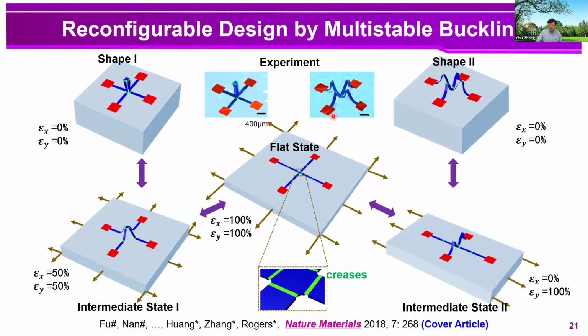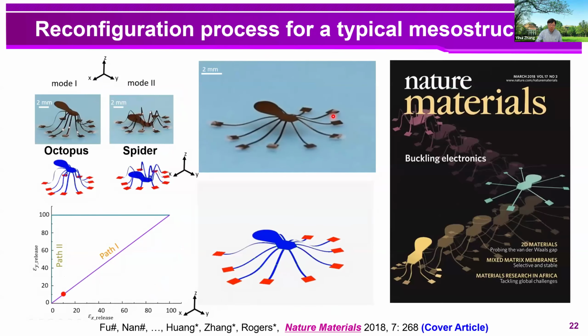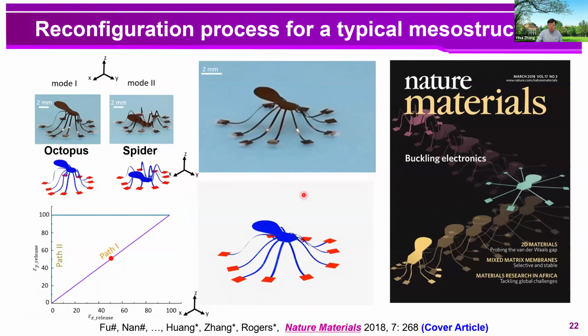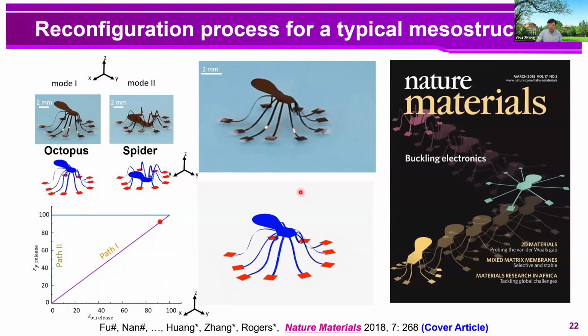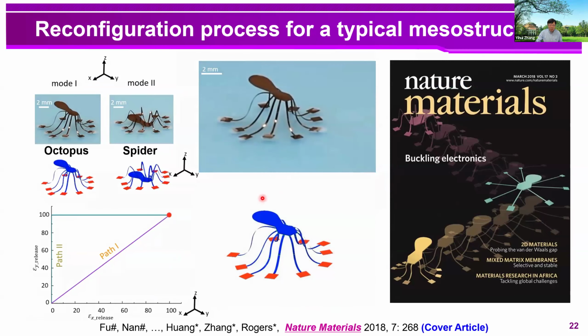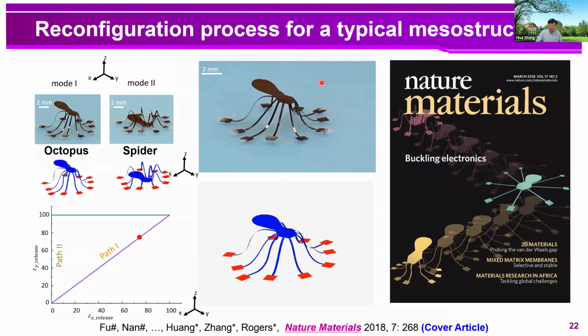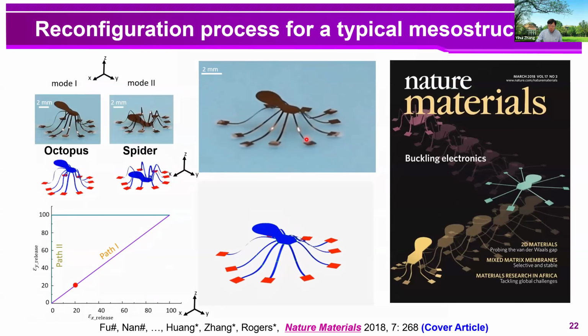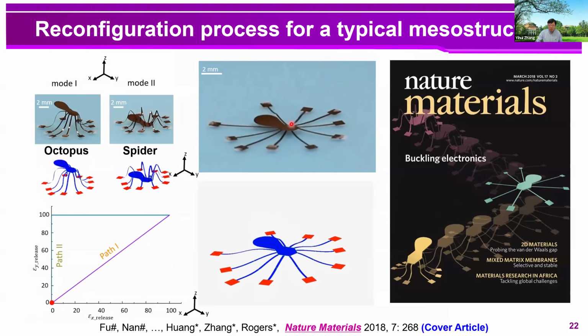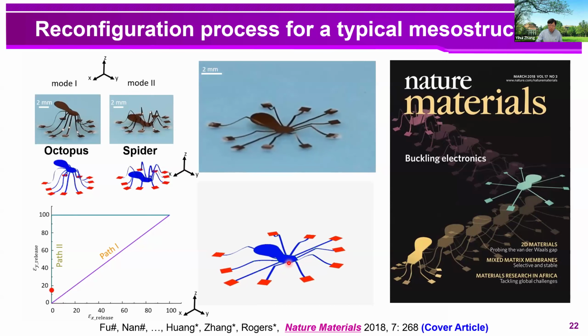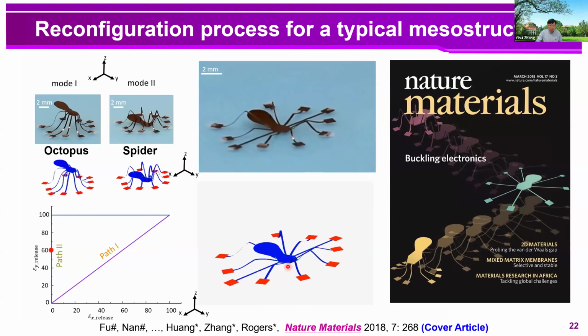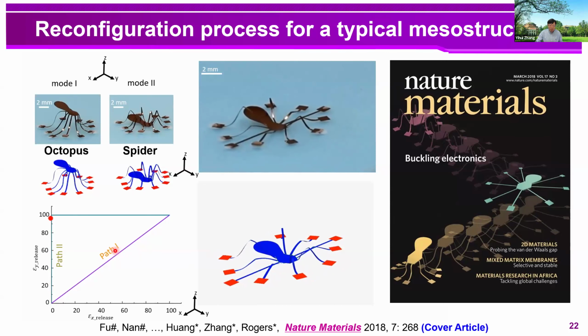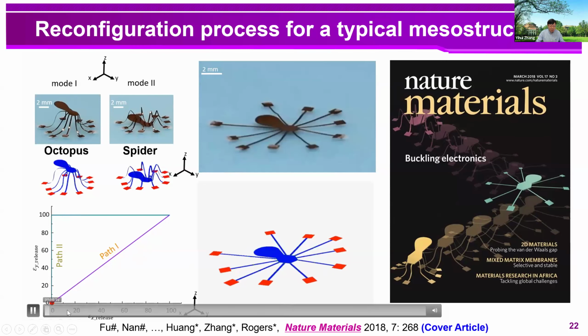And this kind of loading path control strategy can be used to achieve more complex reconfiguration process. And this one shows an example that corresponds to a structure that can be reshaped between an octopus and a spider. And this one shows the experimental results in metal with a lateral size of several millimeters. And this one shows the finite element simulation results. And this one shows the loading paths. So here, we can play the video again.